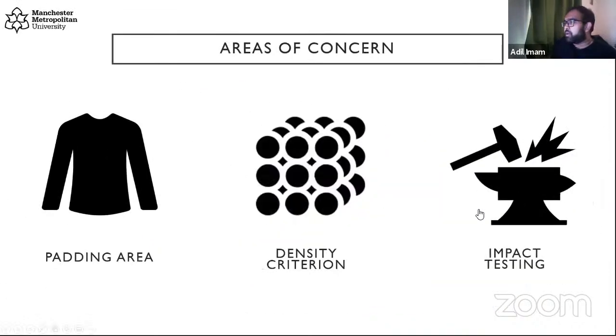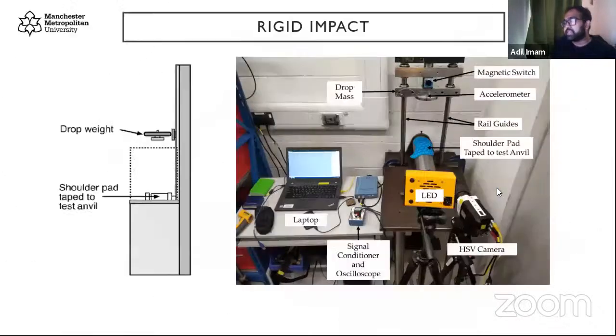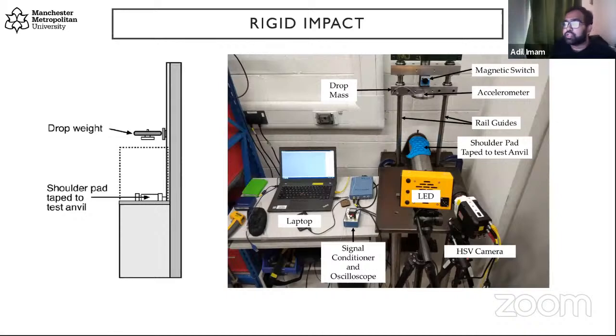So beyond that, the third thing we found that was a concern was the impact testing. Now, the impact test set up in the regulation defines a steel plate dropping onto a steel anvil, and you place the padding in the middle to check if it does not offer too much protection. Now, it is not, you'd never find a steel-on-steel impact during a rugby game. So it is a little bit unrealistic. It is repeatable, but unrealistic.